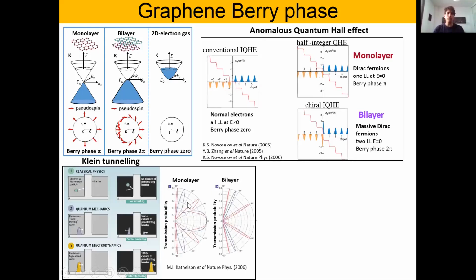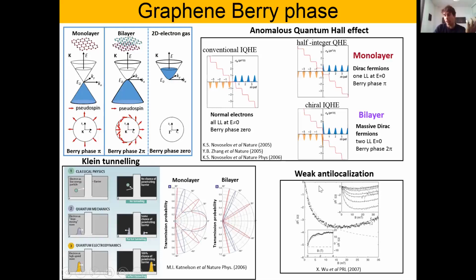And also, due to the Berry phase, it is very difficult to confine graphene's massless Dirac quasiparticles. For example, if you try to use electrostatic confinement for massless quasiparticles, there will always be a direction where electrons can escape. So it is very difficult to confine them with an electrostatic potential. And a related issue is weak anti-localization, which says that backscattering cannot exist for many types of scatterers, so it really affects and influences the transport properties of graphene.